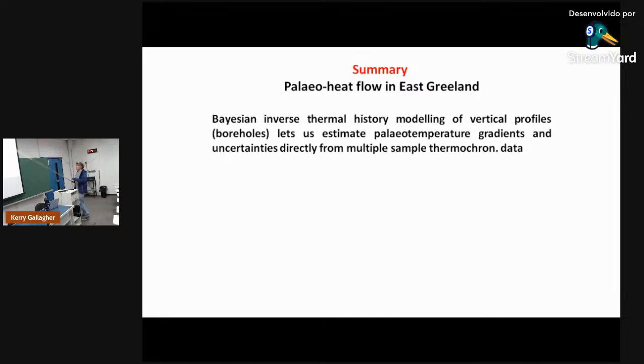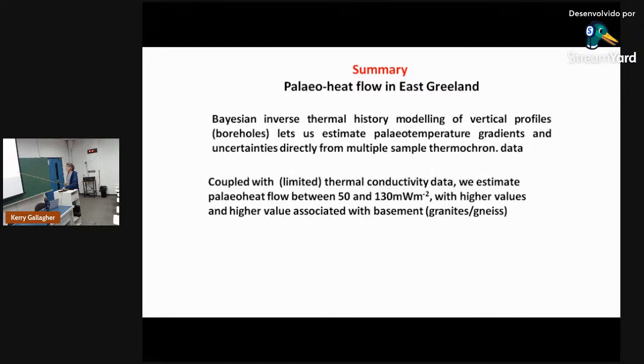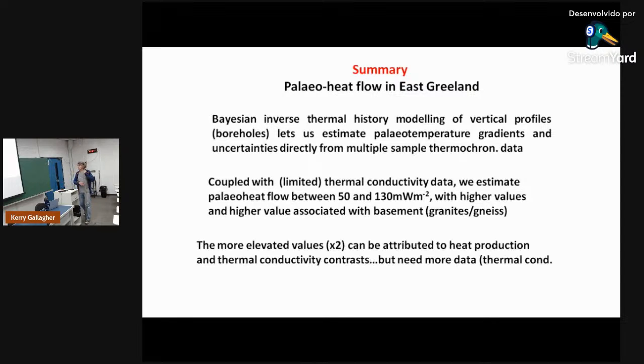So the idea of the Bayesian modeling is we can calculate these temperature histories, and effectively the temperature gradient and its uncertainties, directly from these thermochronological data. We've estimated heat flow values between 50 and 130, it could be about 140 actually, milliwatts per square meter, with the higher values associated with granites and granitic gneisses, which tend to have high heat production and high thermal conductivity.